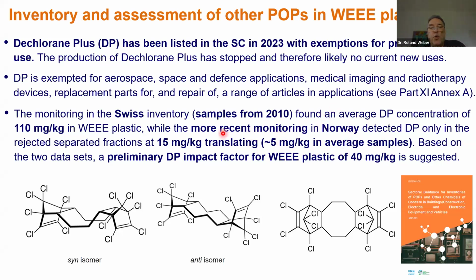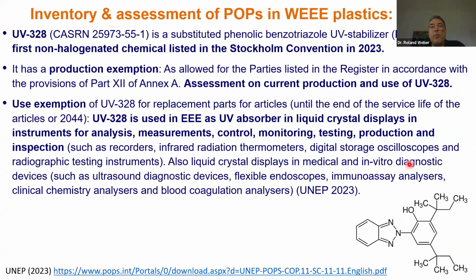So based on these two studies, we have proposed a preliminary DP impact factor for WEEE plastic of 40 milligram per kilogram. But yes, more data are needed. As a first rough estimate, it is good, and I would say that it's good by a factor of 3. Then UV-328 has been listed. UV-328 is a substituted phenolic benzotriazole UV stabilizer. It is the first non-halogenated chemical listed in the Stockholm Convention, in 2023.